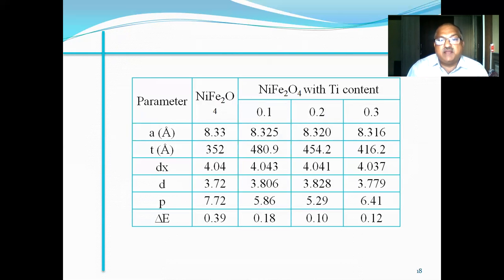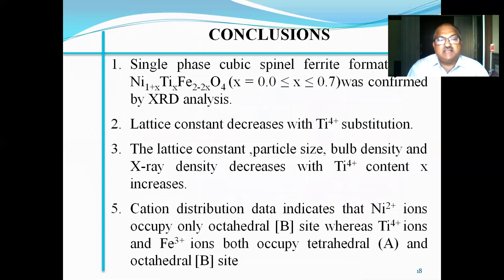These are the parameters calculated for this nickel ferrite: lattice constant, porosity, bulk density, etc. Lastly, I would like to draw some conclusions. Single phase cubic spinel ferrite was confirmed by X-ray analysis. Lattice constant decreases with Ti4+ ion substitution. The lattice constant, particle size, bulk density, and X-ray density decrease as Ti4+ content x